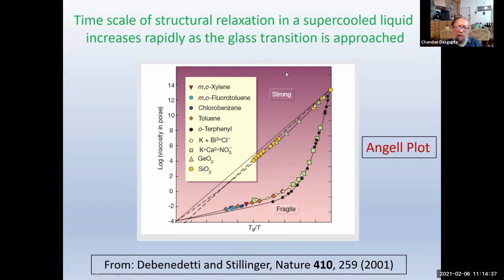And in particular, there is this distinction between fragile glass and strong glass. The fragile glass is one that shows this strong curvature in this plot, and the strong glass is more or less linear. Linear basically means that the log of the viscosity is proportional to 1 over temperature. So that is the usual Arrhenius form. So strong glasses exhibit Arrhenius growth, whereas fragile glasses exhibit faster than Arrhenius growth.